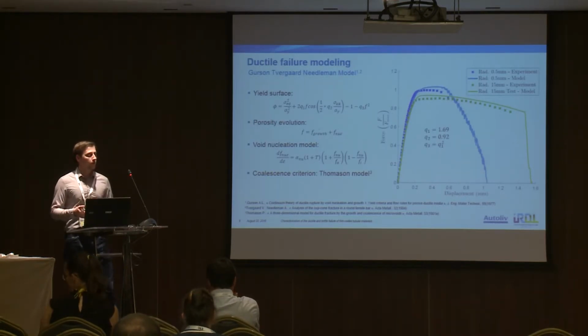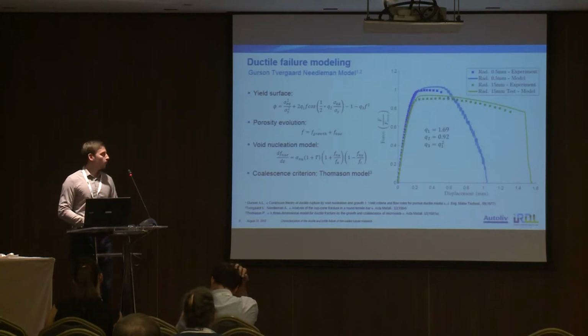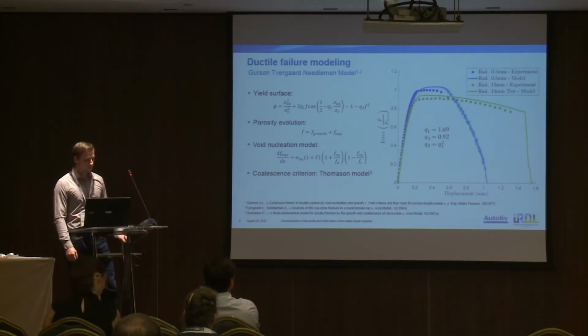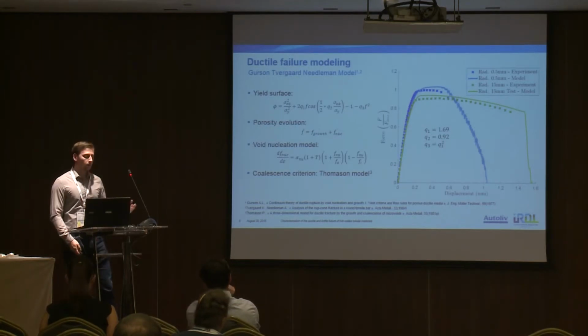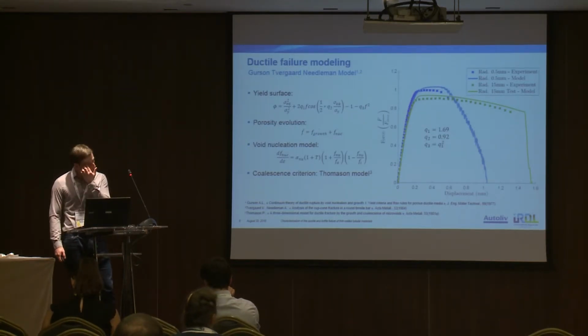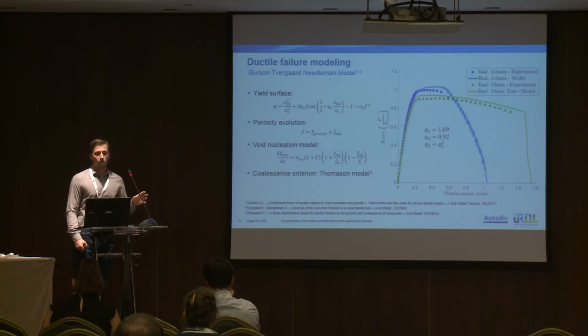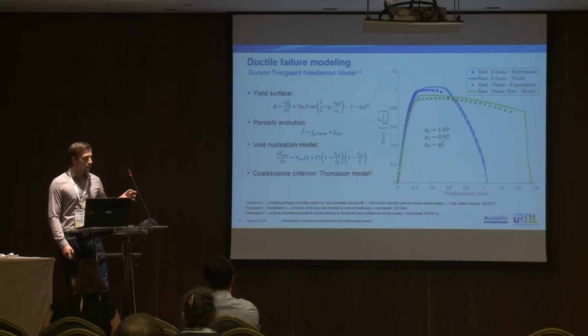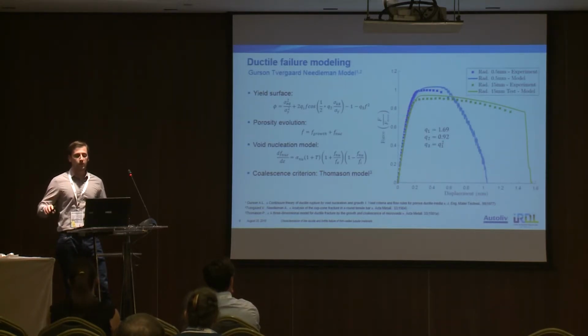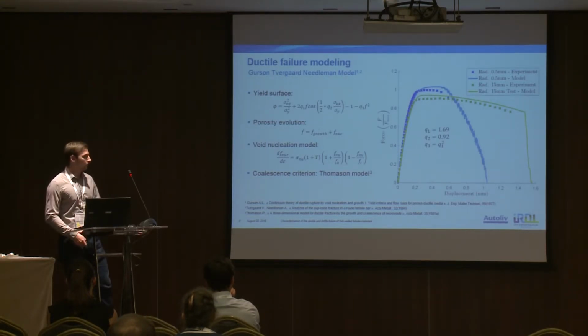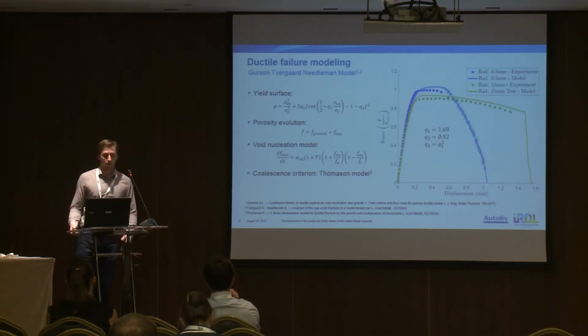We are using the famous GTN model, where you can find the expression of the yield surface here, and then we make 3 different modifications. The first one consists in splitting the porosity evolution in 2 parts. One part is from void growth, and the other part from nucleation. And for the nucleation model, we were using a very recent theory proposed in a recent PhD thesis, less than 1 year old. If you have any question, I will answer at the end of this presentation, of course.